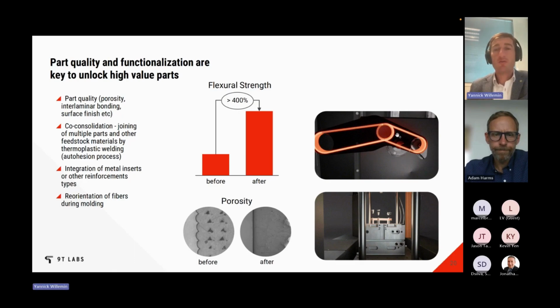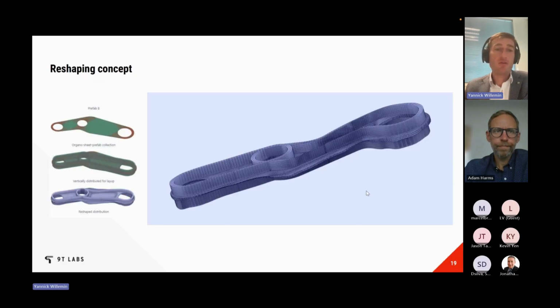On the right side at the top, you see how we would approach such a part. Such a rocker link has 3 attachment points where we would put metallic inserts for the interfaces, and around those 3 points, we do these loops, which are printed with continuous fiber. The remainder of the material is neat or short fiber reinforced. Then we place this shape into the mold, and while applying pressure and temperature, doing the consolidation, increasing interlaminar strength, reducing void, we also reshape the part to the final shape, as you see here a bit.